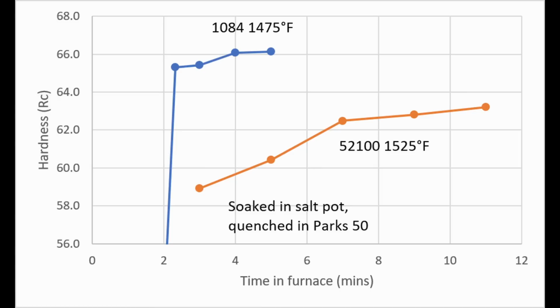So with the 52100, with the same 3-minute hold as 1084 that had nearly 66 Rockwell, the 52100 was still only 59. And then that increased up to a 7-minute hold where it was a little over 62, and then it basically leveled off, and the further increases in hardness were much slower at that point. And this is why I usually don't recommend trying to do soak times that are as short as possible. I prefer to use a longer soak time to ensure that we are in this region where the steel has leveled off, where we're not seeing big changes in hardness with small changes in soak time.